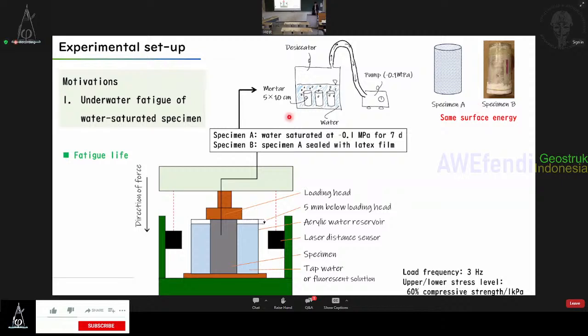So we prepared 2 specimens. Specimen A is mortar saturated with water at negative pressure, and specimen B is sealed with latex film. Latex film is number 1 Japanese technology from Okamoto company. I give a photo like this. In that case, specimen A is of course fully saturated, and specimen B is also fully saturated with water. So that means the same surface energy in the specimen. And what will happen after fatigue?